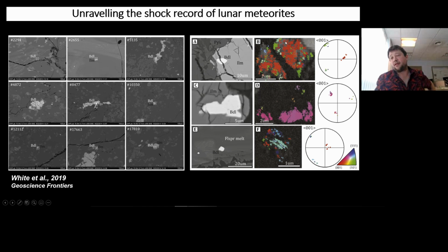So you can see here some are single orientation. So when you look at the pole figure and you start to see these orthogonally related clusters, that's giving you a hint of phase heritage. So that idea that there was one cube, and that cube is broken down into 3 orientations on each of the cube faces, which would be 90 degrees apart. So evidence of high temperature or pressure. In this case, it's in a feldspar melt, so we're probably looking at high temperature effects, or again high pressure, depending on the history of that grain, and you can pick out these clusters. But you can see even in this 1 micron sized grain, tiny baddeleyite, there's a lot of variation. If you were taking a bulk spot, something like a TIMS extraction, what would you be dating here?